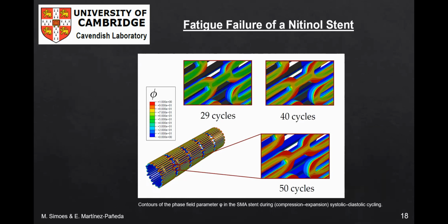While the phase field reaches high values during the deployment stage, 29 cycles of compression expansion pressure are needed for cracks to initiate. These surface cracks initiate in the regions where phase transformation took place during stent deployment. The crack region, phi = 1, extends with increasing number of pressure cycles. And after 50 cycles, it has extended over a significant part of the stent, including the bridging areas between struts. So in summary, the example demonstrates that the framework presented here can be used to estimate the lifetime of medical stents for arbitrary geometries, boundary conditions, and material properties.